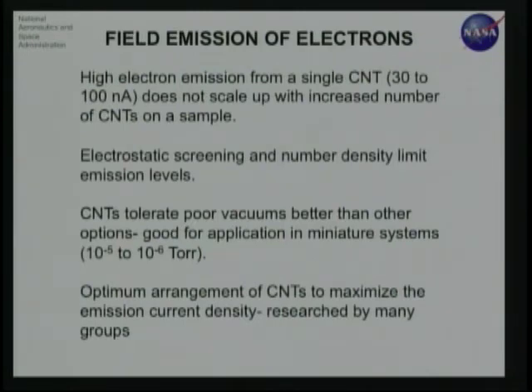One of the reasons why we wanted to do this is because when you do miniature instruments, you need them to operate in vacuums, and these vacuums are miniature cavities. In those cavities, if you've done any micro machining or made micro cavities, you know it's very difficult to achieve extremely good vacuum in a small volume. So you need these field emitters to operate very well in the small volume. That's one of the reasons why CNTs work well, because there is a natural redundancy of multiple emitters being there.